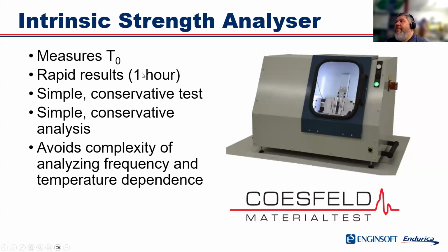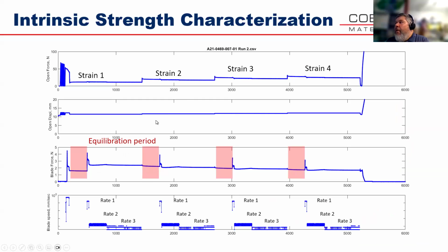It gives you results in about an hour or two that give you T naught. It's a simple conservative test. And like I said, in the other method, you would have to do a fatigue test and reduce the crack growth rate sufficiently that you're approaching the threshold. The problem is that takes a long time. So this is a very fast and efficient test. And here's what it looks like to run the test.